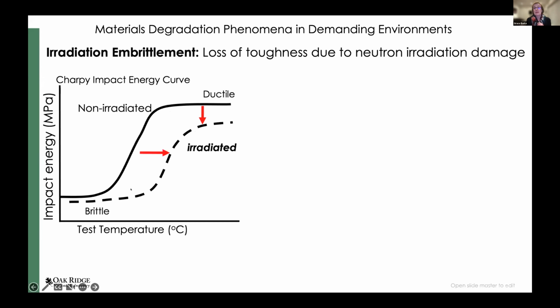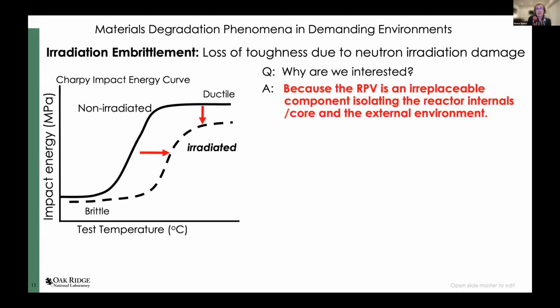When we irradiate it, we can have a shift. So the important part of this is where we used to have ductile behavior, we now can have brittle behavior. And that is what we want to avoid, and we want to understand how this happens. The reason that we are interested is because the reactor pressure vessel, which is the containment structure for a pressurized water reactor, is an irreplaceable component that isolates the reactor internals and the core from the external environment.